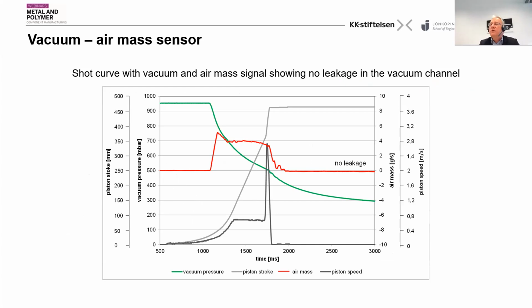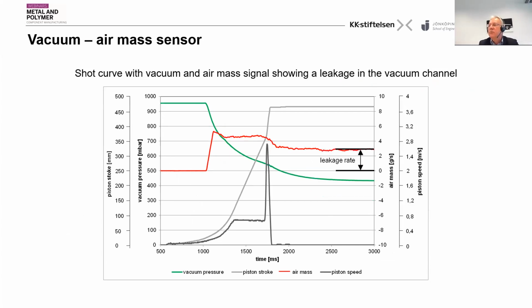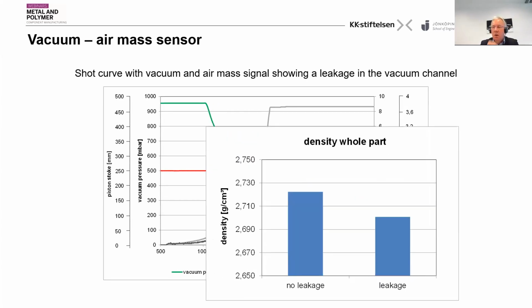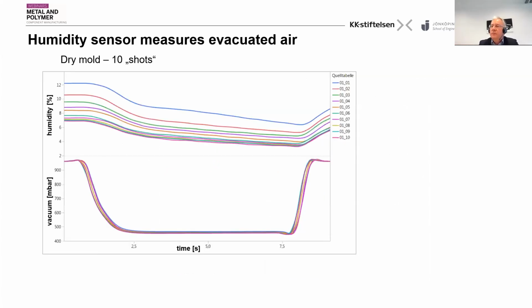It's a very innovative new sensor, and I will show you some results, and residual gas. What we see here is a shot curve with vacuum air showing no leakage. You can see here in this sensor the air mass. It's not the pressure. Vacuum pressure is the green line, and the gray lines are just piston speed and pressures. And here you see the same with a leakage rate, and you can clearly see a big difference, which does not show up so clearly in the green curve, but the air mass clearly shows the difference. And of course, we also measured densities, and this is clear: no leakage, and leakage, you get a big difference in density of the whole part.